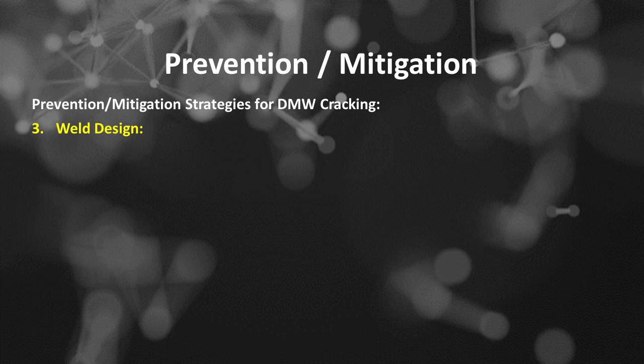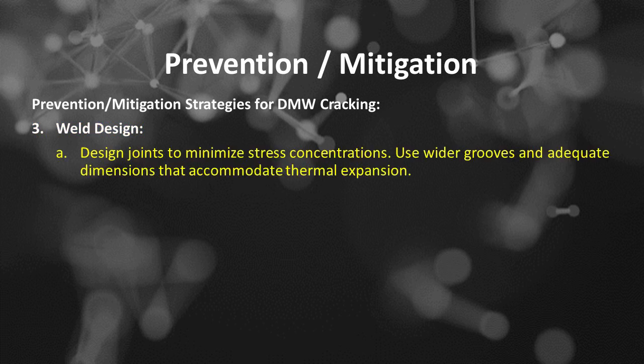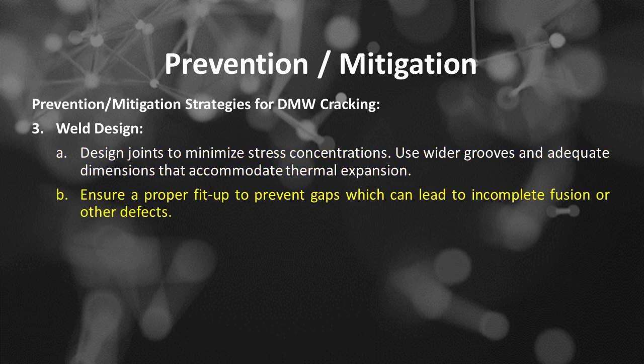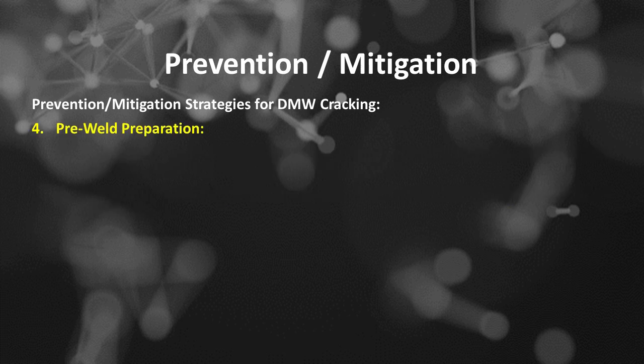Include: the first is design joints to minimize stress concentrations. Use wider grooves and adequate dimensions that accommodate thermal expansion. The second is ensure a proper fit-up to prevent gaps which can lead to incomplete fusion or other defects. Number 4 is pre-weld preparation.